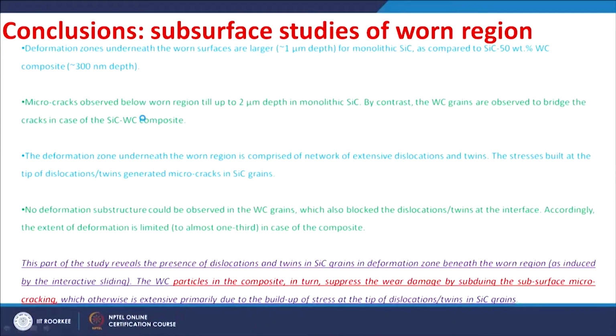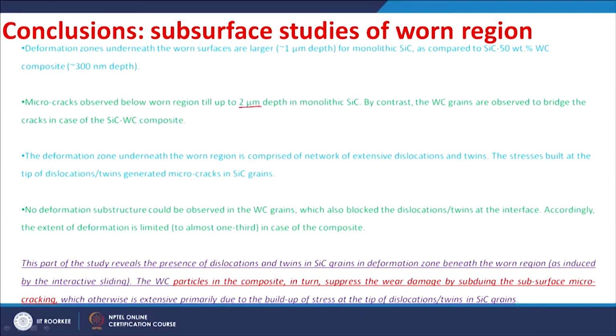So, concluding the subsurface study results, the deformation zones underneath the worn surface are larger for monolithic silicon carbide as compared to the silicon carbide tungsten carbide composite. It is more or less 3 times more for the silicon carbide ceramics as compared to the silicon carbide 50% tungsten carbide composite. Micro cracks are observed below the worn region till 2 micrometer depth for monolithic silicon carbide ceramics. By contrast, the tungsten carbide grains are observed to bridge the cracks in the case of the silicon carbide tungsten carbide composite.